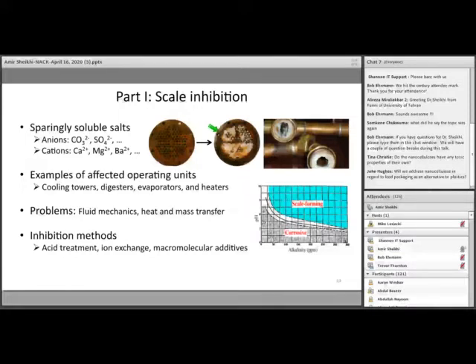The way that the industries have been treating scale can be categorized into three main methods. Acid treatment: some industries used strong acids to dissolve some kinds of scales. Despite the fact that some of the scales can be dissolved in strong acids, we should notice that at low pH conditions, corrosion will be a serious phenomenon. So it's not a favorable event. Ion exchange membranes have been used for this purpose to simply remove all the ions that precipitate, but they are highly expensive. And macromolecular additives have been the gold standard in the field to add to water and prevent the formation of this scale, as compared to waiting and then removing these scales after their formation.